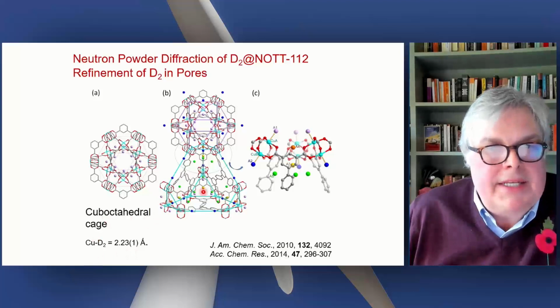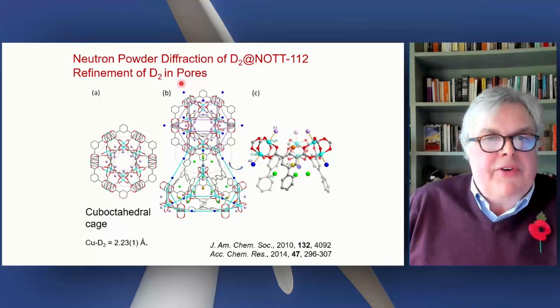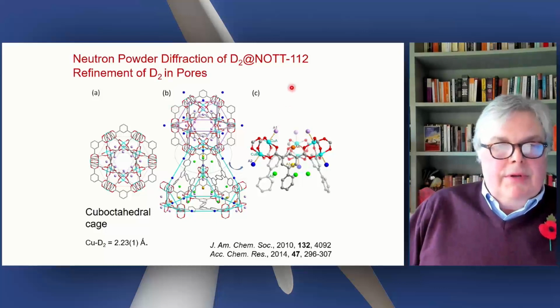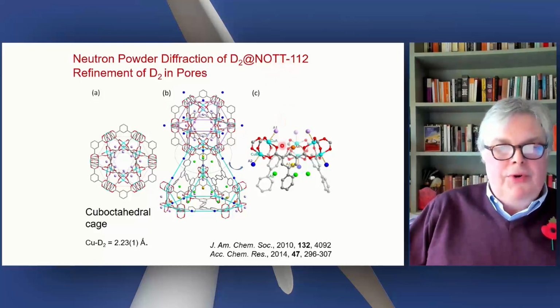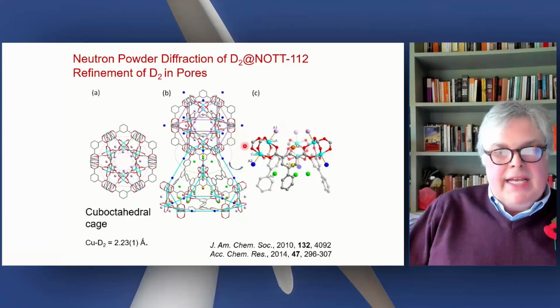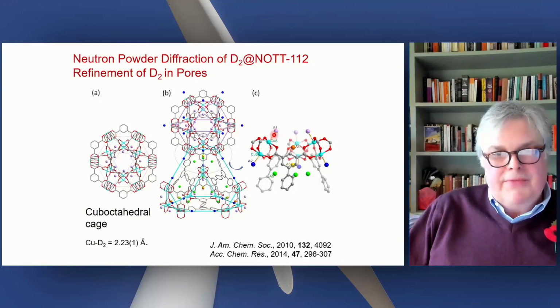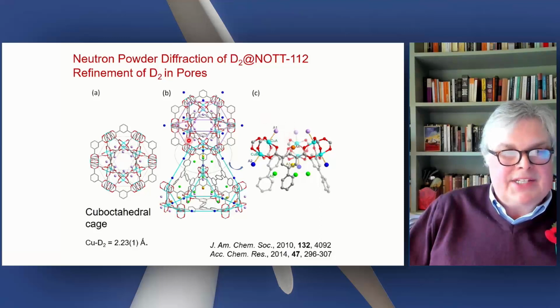You can also analyze where the hydrogen, in this case deuterium, resides within the pores. So this is MFM-112. You can see the binding sites as determined by neutron powder diffraction. A1 is the first site, and it binds to the copper center, which has a vacant coordination site. The second site is the other copper, because these two coppers, this is a copper paddle wheel, these two copper centers are not equivalent because one resides inside the cage and the other one resides outside the cage. So these copper centers are different.